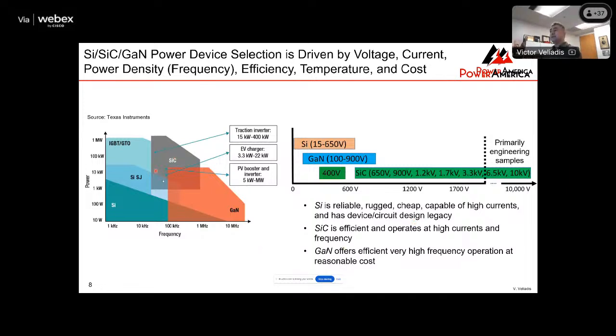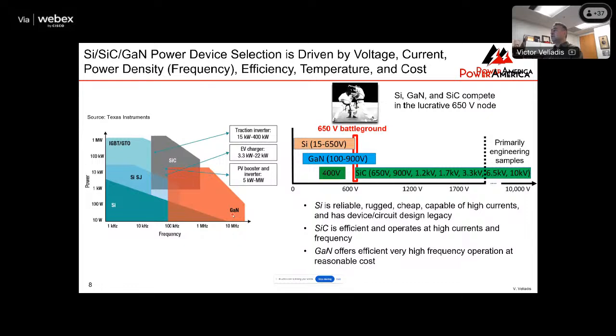If you look at silicon carbide right here, it's efficient at higher frequencies, and it can do high powers. And then if you look at gallium nitride, it can go to even higher frequencies than silicon carbide very efficiently. So there is this 650 volt area, which I call the battleground, because all three, silicon, silicon carbide, and GaN, are extremely competitive. Now, you will notice that there's a 400 volt silicon carbide device that has recently become available from Infineon, and this device is meant for data center applications.